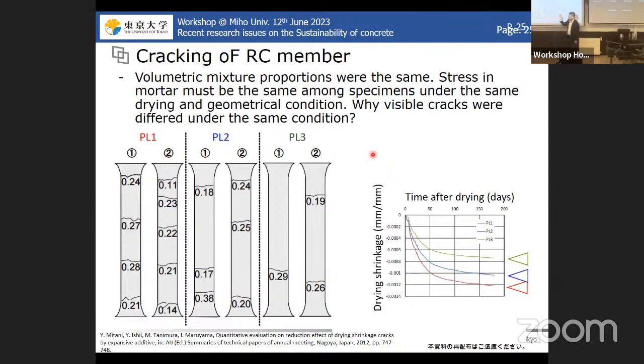And if we reduce the shrinkage by using the non-shrinkable aggregate, we see the reduction of the shrinkage in the cracking. But please think about why this happens. Because if the main source of the shrinkage is the hardened cement paste, and it is restrained by the outer frame, and we put the aggregate inside, why does this different kind of shrinkage happen? So that is my question on this topic.